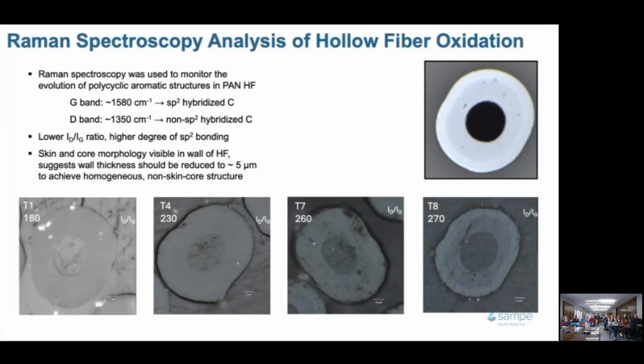Interesting on the hollow fibers that we have been able to produce: in the upper right, you'll see this is an optical microscope image of the fracture surface, just looking straight down one of these hollow fibers. You'll see that there's this bright band around the exterior of the filament, almost a clear front in between, and then this darker material inside. We posit that the outside is well-oxidized material, which is reflecting more photons because of its conjugated bonding compared to the material on the inside.